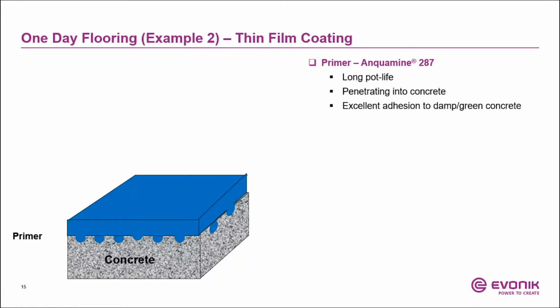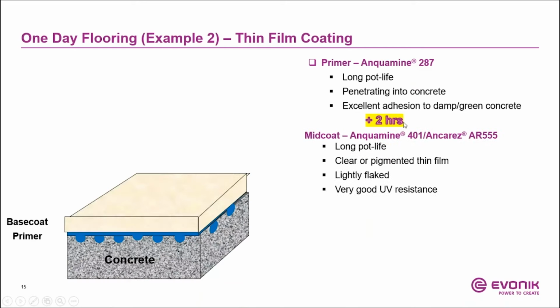This product has been around for a long time and has been successfully used over concrete because it does penetrate into concrete, so it's forming a really good bond. It has excellent adhesion to damp and green concrete. Another benefit, again, you have long pot life, so improved workability, but it also cures very quickly. After 2 hours, you're able to apply the base coat.